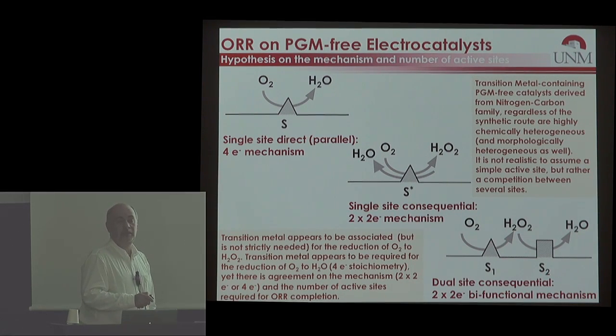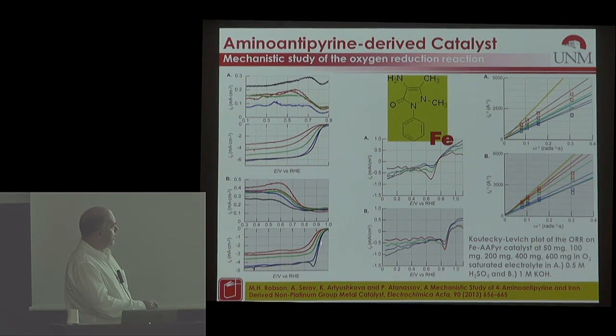That is why when somebody makes a very bad catalyst, then actually the plateau in the rotating disk electrode goes down to 10, 12, and they claim great activity. No, you just made oxygen locally. And that's why you are recording limited diffusion current densities that do not correspond to the amount of oxygen dissolved in your electrolyte. It is stupid to claim the diffusion limiting current as an activity. It never has been an activity measure.